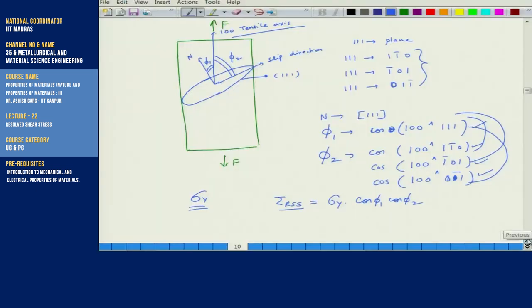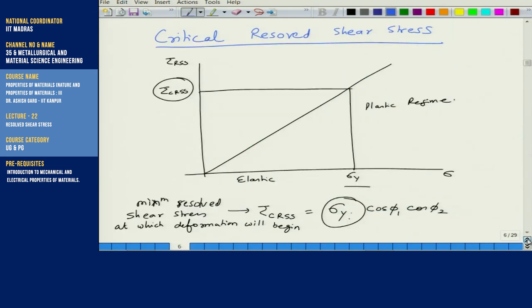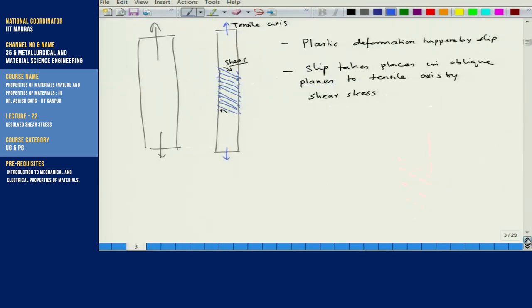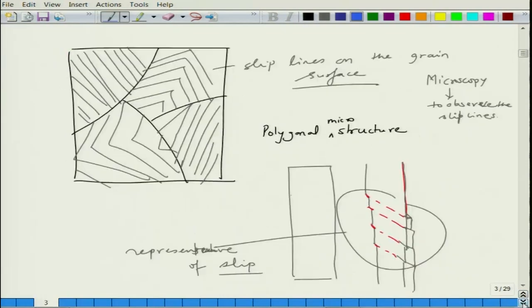What we have done in this lecture is, we have just looked at the concept of resolved shear stress. So, basically what we see is that you have slip lines on these crystals, and these slip lines are at a certain angle to the tensile axis, and this can be easily seen in the microscope. So, basically what we are saying is that when you apply tensile stress, since the slip direction and the slip plane are inclined with respect to the tensile axis, there is a shear component acting. So, we took a model of a single crystal system with a slip plane in it with respect to the tensile axis, and we worked out the resolved shear stress